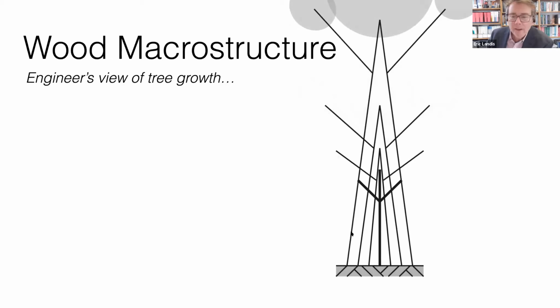And this is significant for several reasons, but in fact, the structural properties change as the tree grows. Towards the center, we have what we refer to as juvenile wood, and there the wood tends to be a little more compliant, because it's better for resiliency if the tree can flex a bit. But of course, like with skyscrapers, as we get taller and taller, the wood needs to gain some stiffness. And in fact, the wood that's at the outer part of the stem tends to have better structural properties than in the interior.